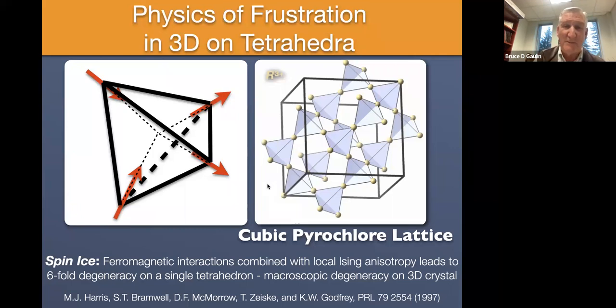So that problem, as I've just described it, was first introduced in this paper here in 1997 by Harris, Bramwell and co-workers. And actually, this is an experimental study of holmium titanate, where it's the holmium 3+ magnetic moments that are arranged on the vertices of the tetrahedron. And they recognized that the disordered state arose because of this combination of ferromagnetic interactions and uniaxial anisotropy. So that's all well and good.